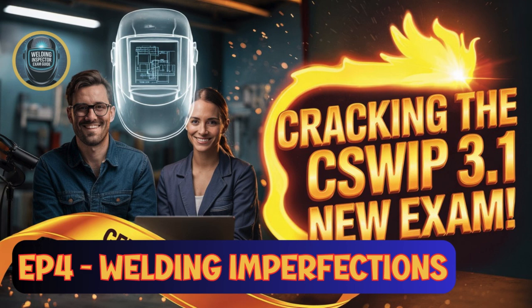Definitely not. Crucially, any weld repair, whether it's just filling a small excavation or sometimes remaking an entire joint section, must be done strictly according to an approved and qualified welding procedure. Yeah. The rigor involved in qualifying that repair procedure depends entirely on the application standard and the criticality of the component. Sometimes it might be a pre-approved standard procedure, but for highly critical applications, it might require an exact simulation of the repair on a test piece: make the joint, excavate the defect, refill it using the proposed repair method, followed by extensive inspection and mechanical testing, essentially proving beyond doubt that the repaired weld is as good as, if not better than, the original sound weld.